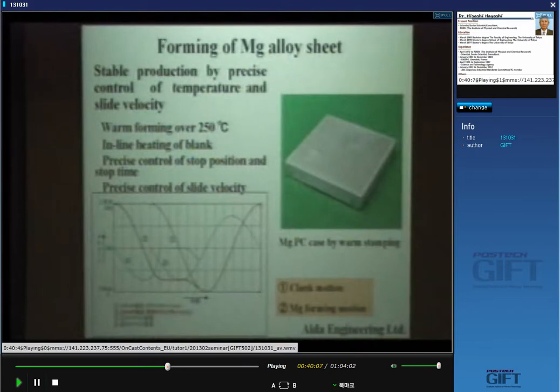And this is also a little old one, for the forming of magnesium alloy sheets developed by Aida Engineering. And when we stamp the magnesium alloys at room temperature, we cannot carry out the forming of magnesium alloys. Usually we need a little high temperature, more than 200 or 250 degrees. So for magnesium alloy stamping, servo-press is good for the control of slide velocity like this.